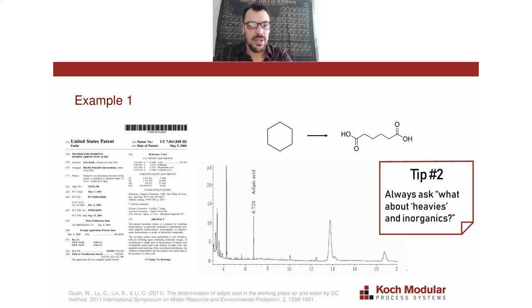The next thing I would recommend is always ask the question, what about heavies and inorganics? If a compound is too large, too high molecular weight, or too high a boiling point, it won't be resolved on the gas chromatogram. It'll just get stuck in the trap on the column. And it's unfortunately been my experience that those compounds aren't necessarily appreciated until much later in the process, perhaps when piloting has occurred and someone's wondering why there's a thick sludgy material at the end of the distillation. This might have been discoverable earlier on if someone had asked, does this chromatogram resolve all the heavies that you're making? And inorganics, similarly, like salts, do not resolve on a gas chromatogram. So you want to ask about those as well, because they will be part of your separations challenge, even if they don't show up on the analytical analysis.